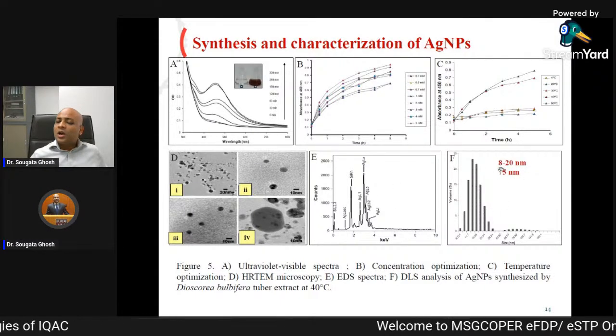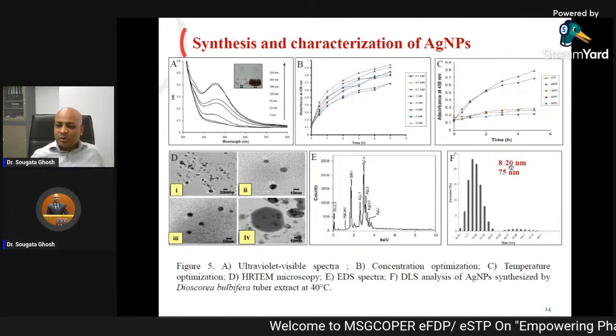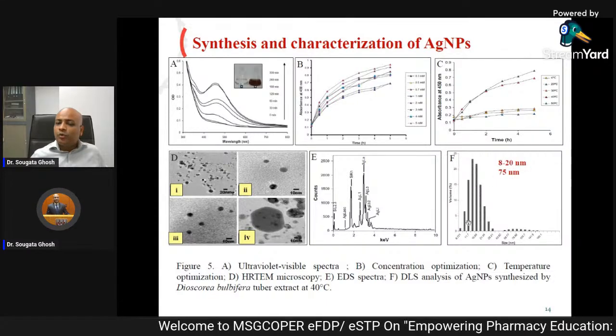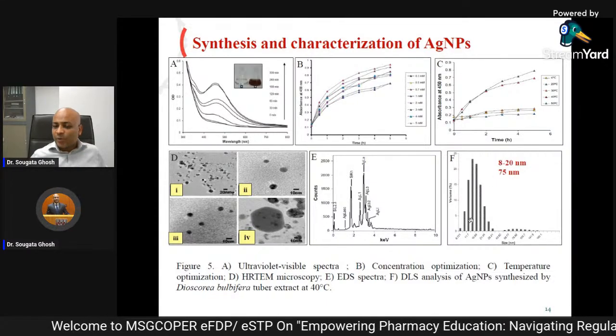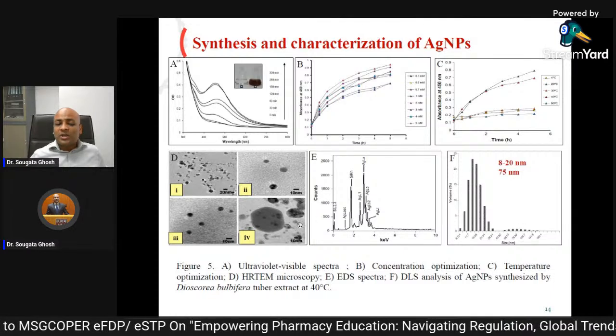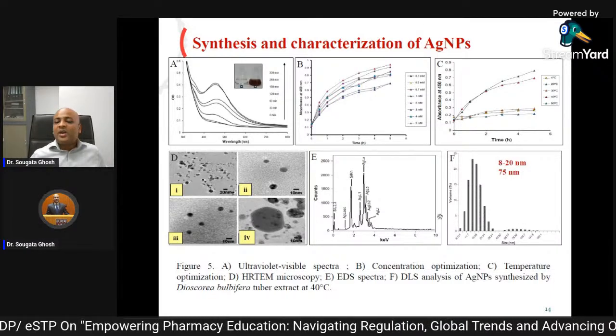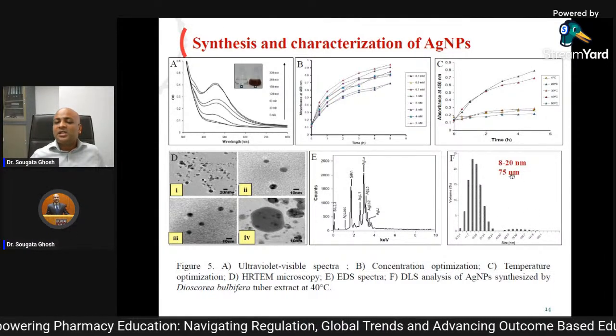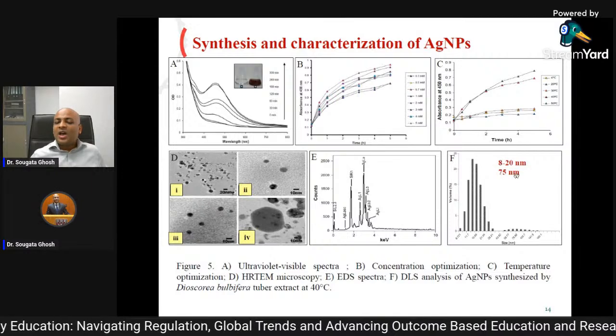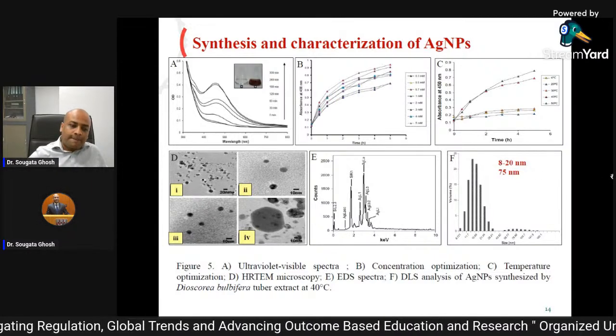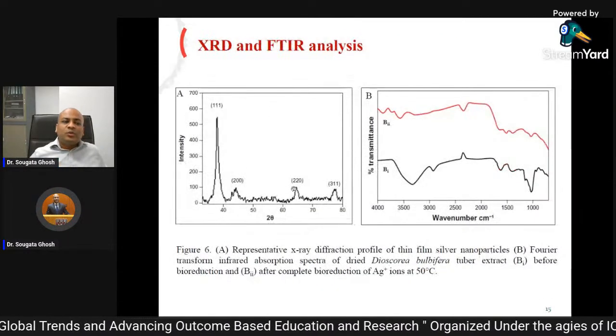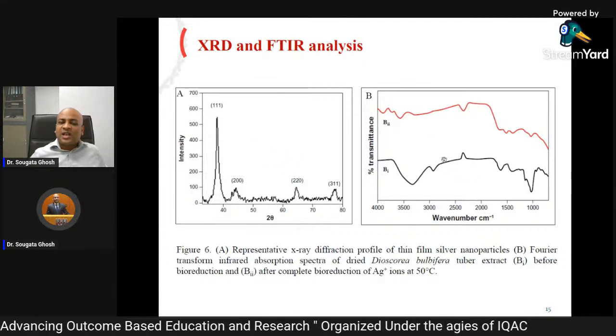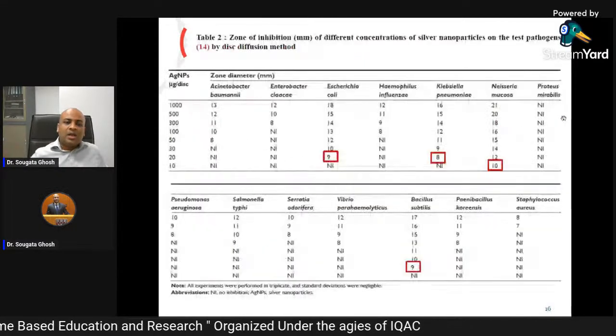Hydrodynamic size also confirmed that 8 to 20 nanometer was the majority over here, 8 to 20 nanometer silver nanoparticles, but they were coming together, as you can see over here. They were coming together to form bigger particles, which were very few, around 75 nanometer. We confirmed its crystallinity with the help of XRD and also FTIR.